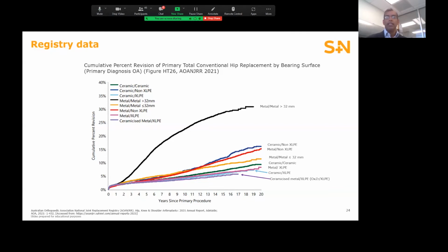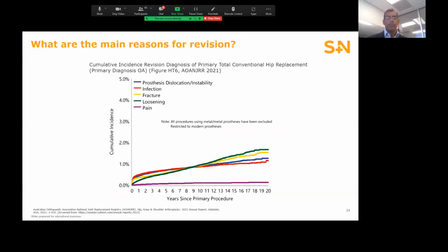One thing that is clearly apparent from this slide is that highly cross-linked UHMWPE outperforms non-cross-linked UHMWPE. Another point of note is that the ceramicized metal group paired with XLPE has the best survivorship of any bearing combination. And this ceramicized metal group consists wholly of oxinium heads paired with XLPE. And I should have mentioned, when I say XLPE, I'm referring to highly cross-linked polyethylene.